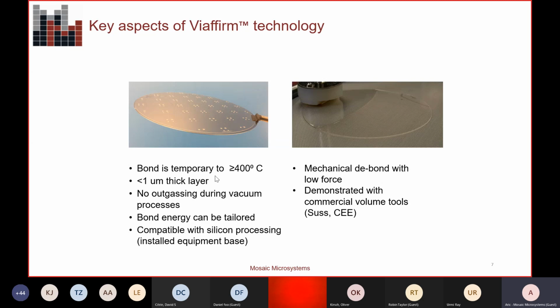So I think I've already talked enough about this stuff. A couple things I hadn't mentioned yet. So the bond energy is on the order of 400 millijoules per meter squared. If that doesn't mean anything to you, it's about 2 times a typical van der Waals bond. But that bond energy can be tailored. So we ended up at 400 as a standard because that was strong enough for processing like CMP and grinding, and weak enough to do an easy debond.